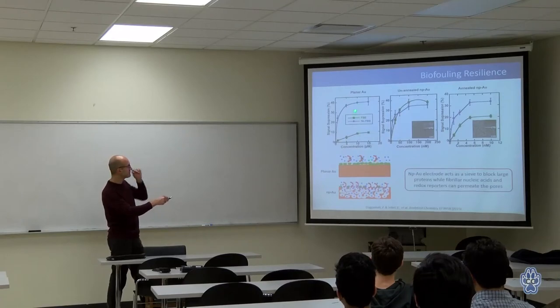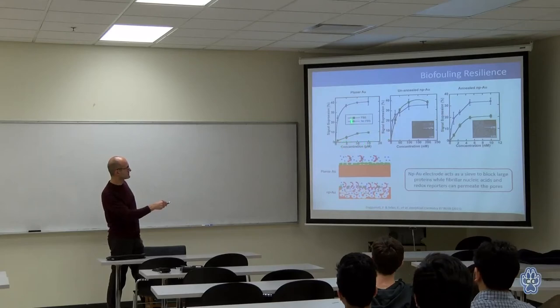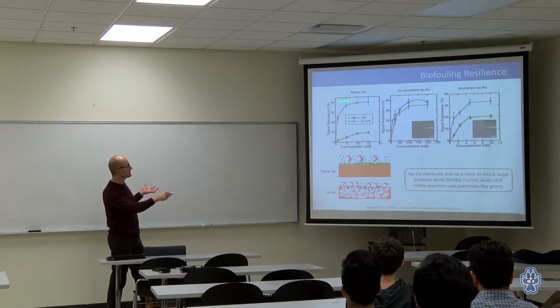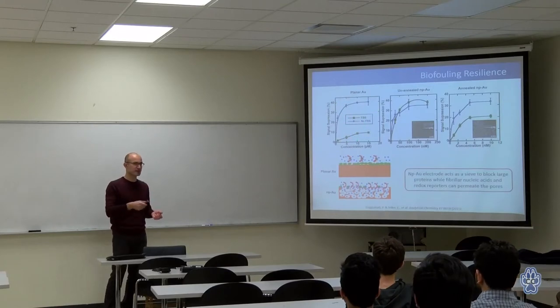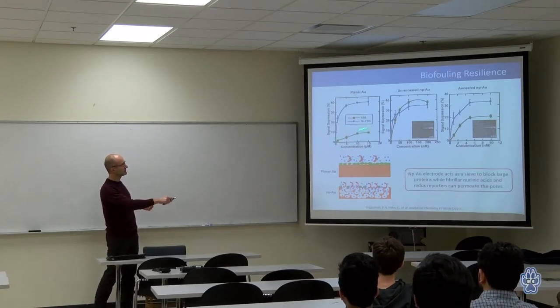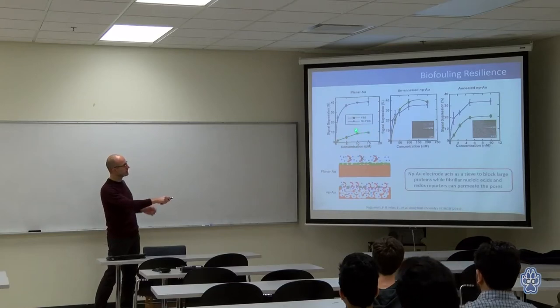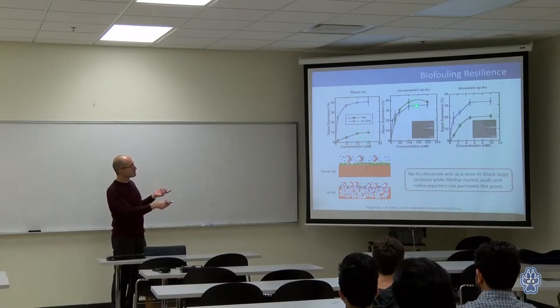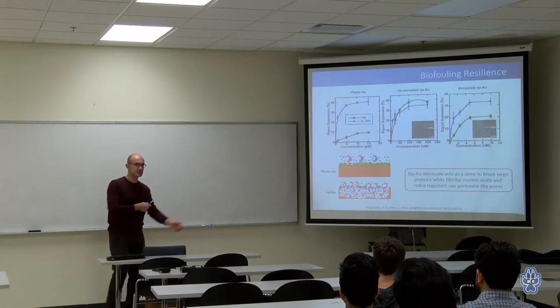The example of it here is, if you have a planar surface, and this is your target concentration, if you are doing it in a solution that does not have any proteins, it's very pure, it works pretty well. You have very large signal suppression. But if you add proteins to it, which is basically serum that you can take from the blood, now the surface is fouled and your signal-to-noise ratio is very low. If you do this with nanoporous gold, it's actually not affected by the proteins. So how is this even possible?